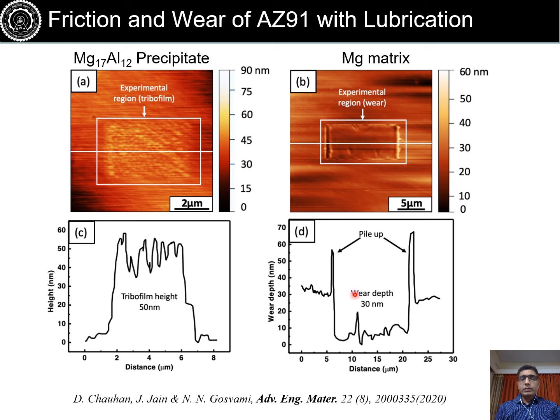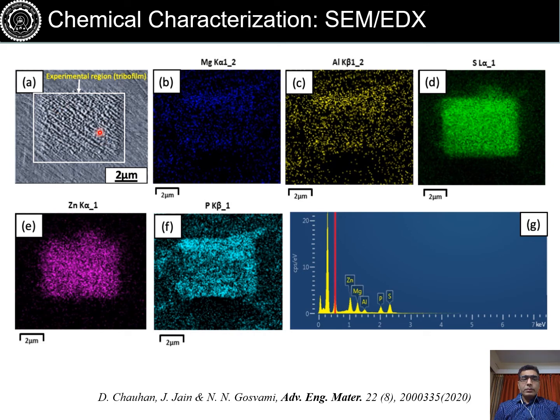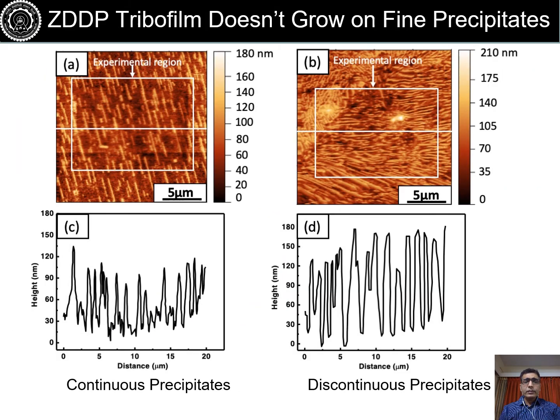Whereas magnesium does not support tribofilm formation, and we always see wear of magnesium matrix. So ZDDP is a very poor anti-wear additive for magnesium alloys because we could never see ZDDP forming a film on magnesium either close to the precipitate or away from the precipitate. We always see wear of the magnesium matrix. Of course, on the precipitate, we characterize the film and we confirm that these films are coming from ZDDP derived species due to presence of zinc, phosphorus, and sulfur. Whereas on matrix, we didn't see any such signals.